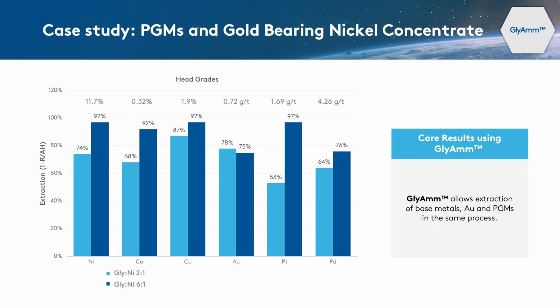increased. Especially for nickel, cobalt, and copper, all of them achieved over 90%, even 97% of extraction. For platinum, there's a big increase in terms of extraction as well, from 53 to 97%. And palladium also increased from 64 to 76%. The key takeaway from this case study is that GlyAmm allows extraction of base metals, gold, and PGMs in the same process.